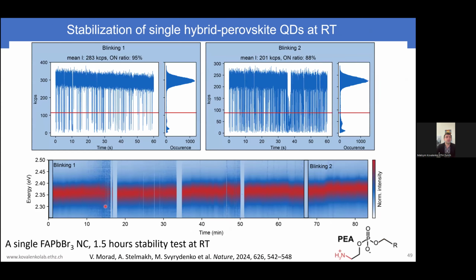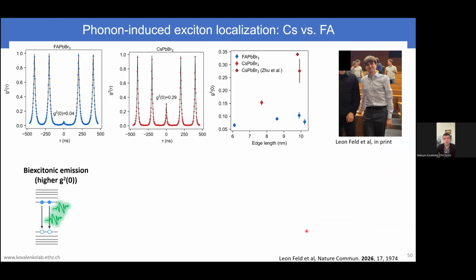That's huge happiness for us back then, because now you can see these for hours. They stay bright, they stay almost fully in the on state. So you see here on to off ratio, they are mostly, they do not blink like stars on the sky anymore. And they are wonderful, stable room temperature, single photon sources. And that's what the student Leon Feld just published and graduated in our group.